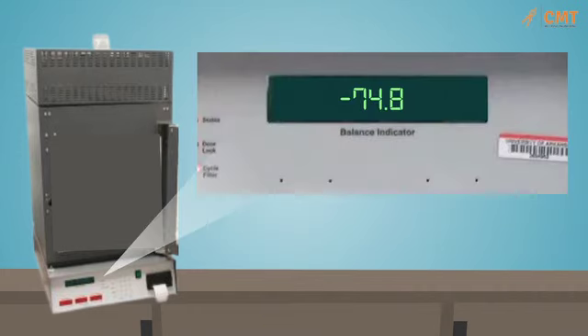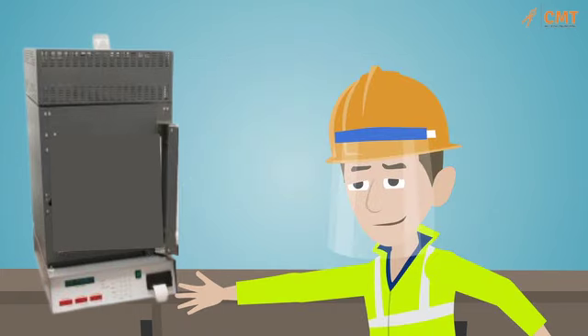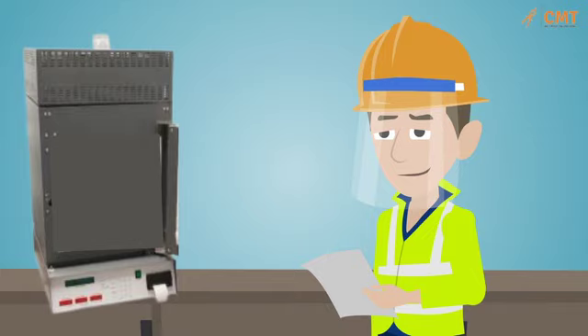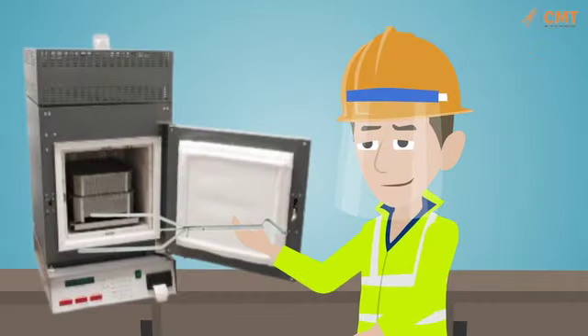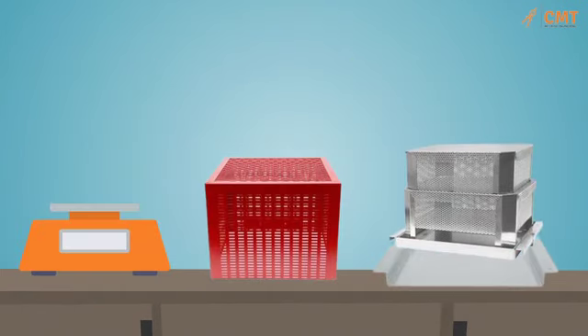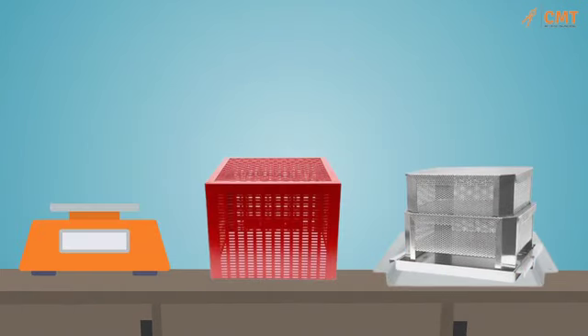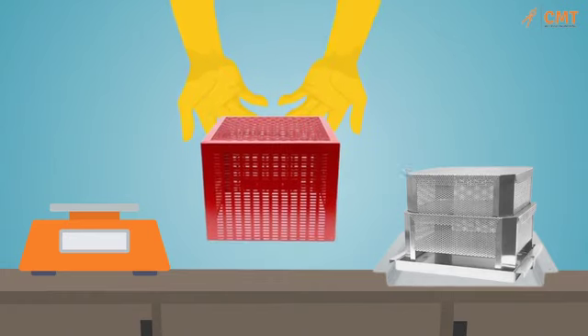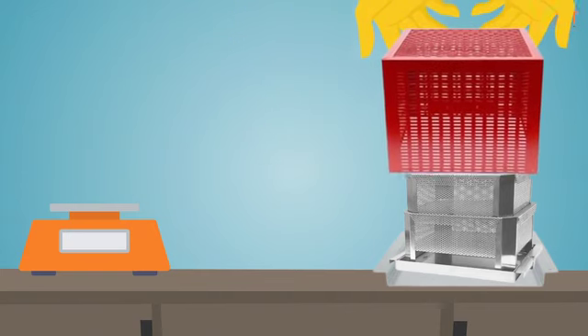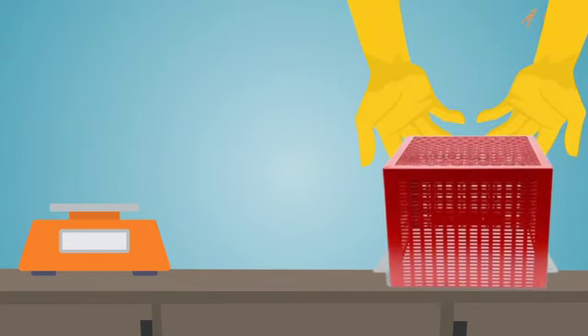When the ignition oven detects no additional loss over a 3-minute time period, the burn is complete. You will stop the burn sequence and collect the data ticket. Then record the calibrated asphalt content from the ticket to the nearest 0.01%. Next, you need to remove the basket assembly from the ignition furnace with the loading fork. Then you will place the basket assembly on a heat-resistant surface capable of withstanding 1,202 degrees Fahrenheit. Make sure to cover the sample with a protective shield and allow the basket and aggregate to cool to room